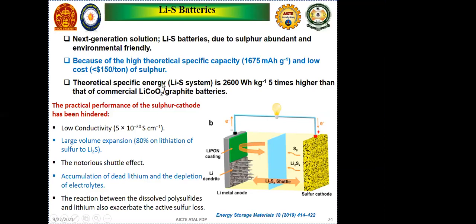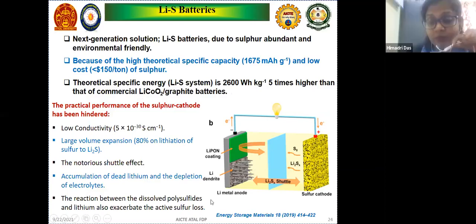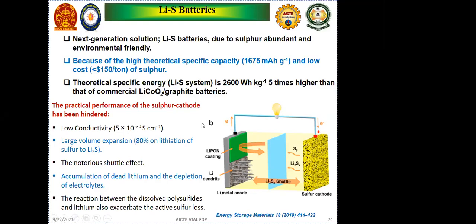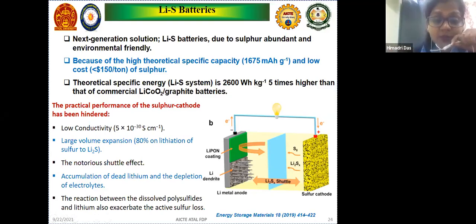Here we can use the lithium and sulfur system, like a lithium anode and sulfur based cathode. And definitely the energy density of the lithium sulfur system will be very high, almost 5 times that of the lithium ion battery. But the issues that practically hinder lithium sulfur battery performance are low conductivity of the sulfur and large volume expansion of Li2S cathode materials, and then instability of the sulfur. As we know, sulfur has various allotropic structures, so in different stages of charging and discharging it gives different unstable materials, which doesn't allow the battery proper cycling.